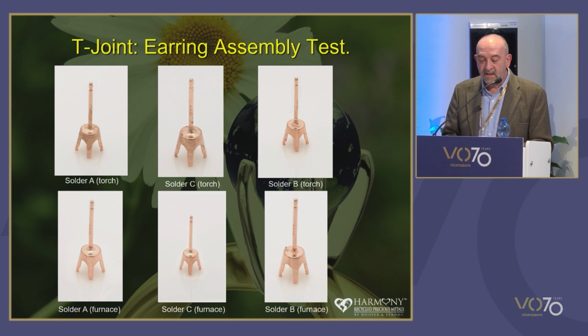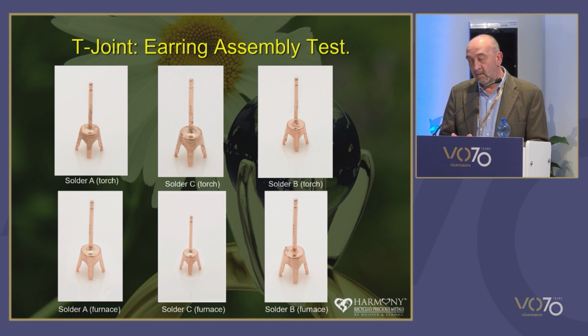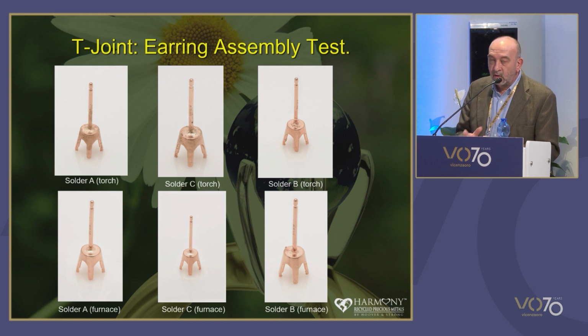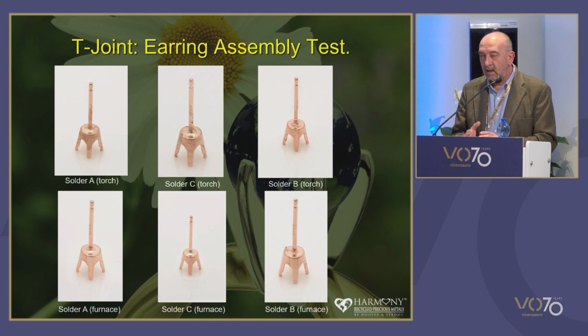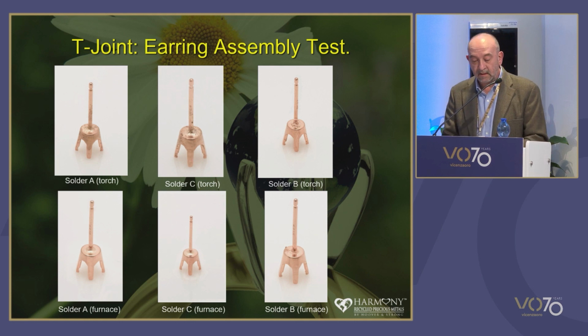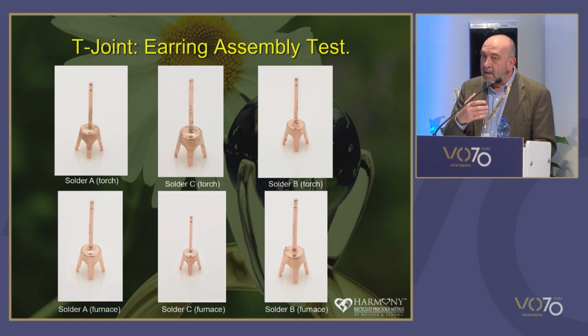So why were these tests better overall than the ring sizing tests? There could be several reasons. First of all, the T-joint has a very close gap because the post is tack welded into position in the first place, encouraging a good solder joint. And also, the relatively low thermal mass of the pieces compared to the rings may contribute to this. And it's going to make the test less susceptible to furnace conditions.